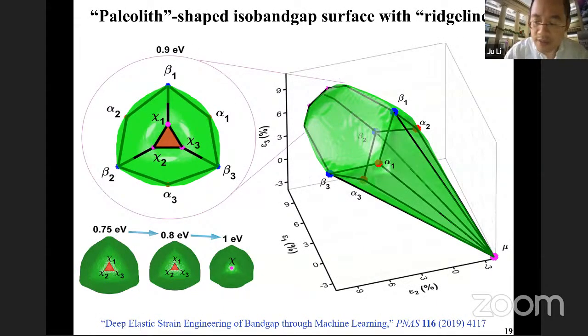And we can use a machine learned model to also look at topologies of band structures. And for mechanical behavior people, this looks like a Tresca yield surface. But what it is really is in strain space. So these are the 3 principal strain axes. In strain space, what strain gives you 0.9 EV band gap? So the iso band gap surface.